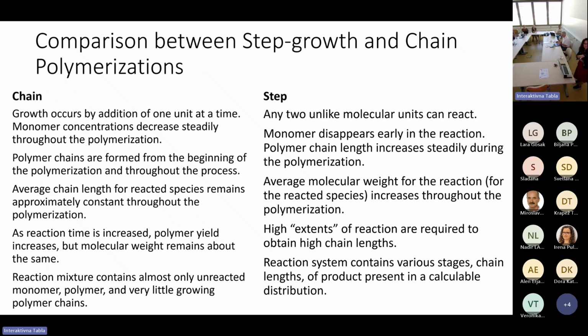That's about it. And the last slide is a comparison between step growth and chain polymerization. For chain polymerization, growth occurs by addition of one unit at a time, so only one unit is added at the end of a growing chain. It means that monomer concentration decreases steadily throughout the polymerization, while in step polymerization, any two unlike molecular units can be added. As a consequence, monomer disappears early in the reaction, and polymer chain length increases steadily during the polymerization.